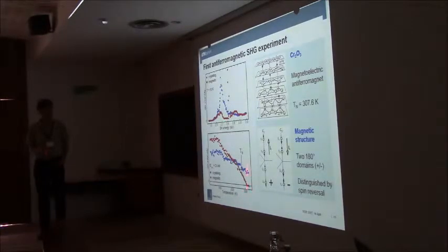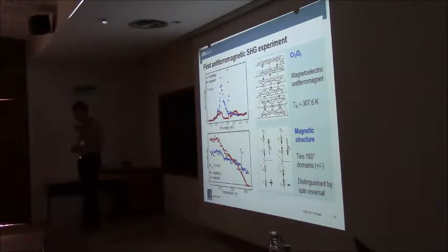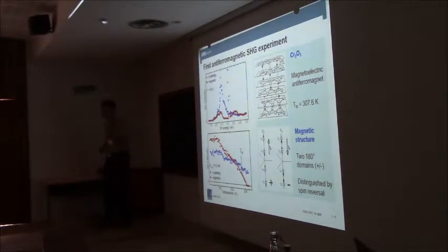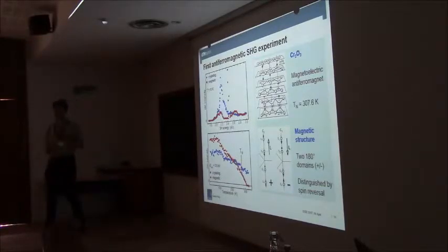So the Néel temperature is here, the ordering temperature. But the red one, this continuously decreases, and right at the ordering temperature, 308 Kelvin, it's gone. So it indicates magnetic order background free. That's the nice thing. Even antiferromagnetic order, which is very difficult otherwise.